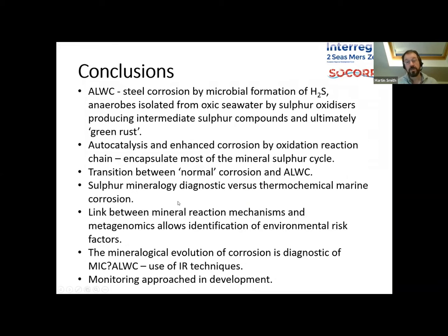So across those two projects, at least the Brighton part, we've recognized and identified the mechanism of accelerated low water corrosion. We can actually see that quite clearly now. We've got microbial formation of hydrogen sulfide, generation of mackinawite and pyrite. That's been oxidized again bacterially through a range of intermediate sulfur oxidation state sulfur compounds, ultimately to produce green rusts. And that's an autocatalysed process.